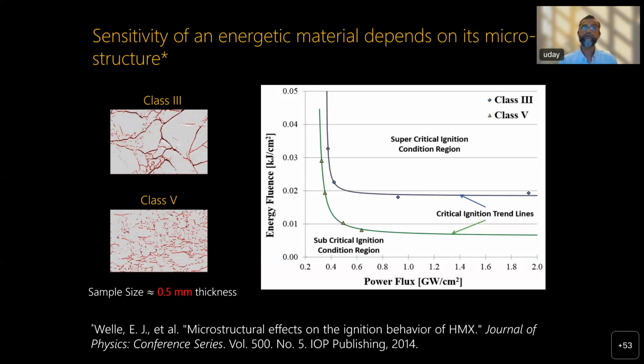And you can see that for two different microstructures, class 3 and class 5 of HMX, this is pressed HMX, the criticality envelopes are very different. That is, the material sensitivity is significantly influenced by the microstructure. In particular, it's influenced by the porosity of the material. You can see that in those microstructures, there are all these cracks and pores and so on. And so the prevalence of these sites determines the criticality curve for these materials.